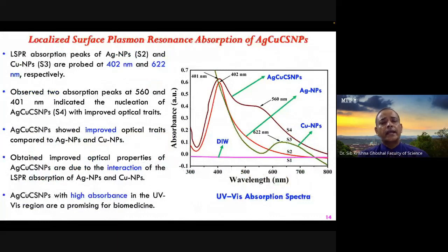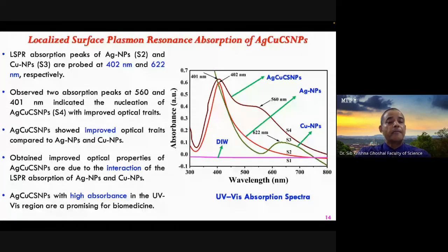Now, if we look at the localized surface plasmon resonance absorption of the core-shell nanoparticles, here you can see how their strong peaks are in different places. For example, the core-shell nanoparticles show two strong peaks, one at 402 nanometers and the other at 560 nanometers. Both of these peaks we can use for different applications.